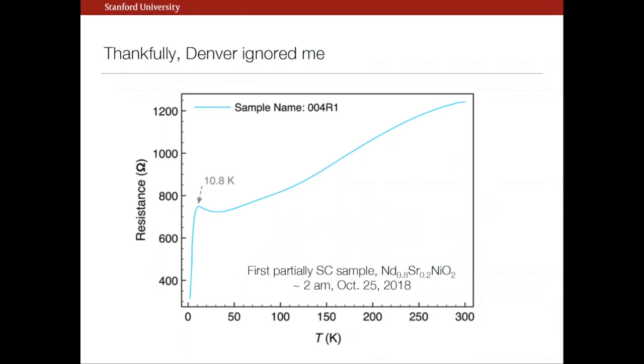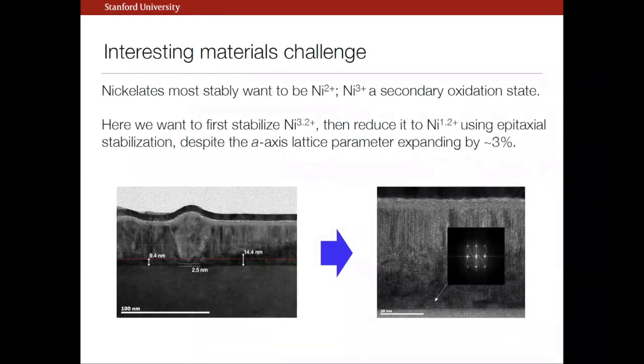And actually, our first paper on this was submitted more than 8 months later, so you may ask what took so long. And I should say this is kind of the most challenging materials issue that we've ever been, or I've been involved in. So in words, I could say the following. Nickelates want to be most stably like nickel oxide, nickel 2+, and nickel 3+ is a secondary oxidation state. So what we're trying to do is to go to a very high, unusually high oxidation state of nickel in this doped perovskite form, and then go to something unusually low. Now we want to use epitaxial stabilization, as we'll show you it's quite integral. But this transformation changes the lattice by 3%.